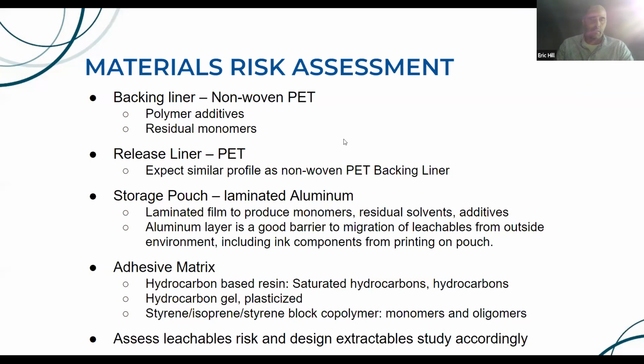And so because we had that aluminum pouch, we didn't do any studies to look for ink migration from printing on the pouch. If this was in a polymer pouch versus an aluminum pouch, we would be concerned about ink migrating through that polymer layer, but it's been well documented that aluminum provides an excellent barrier to ink migration. So in this case, we didn't have to evaluate that.